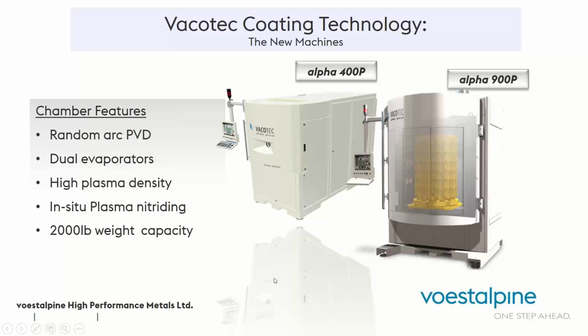It turns. One thing that you need to keep in mind in PVD technology, especially arc technology, is that it is a line of sight process. What does line of sight mean? What it sees, it can coat. So if it's hidden from the view of the plasma field, and the plasma field does travel in a straight line, it will not get coated properly. Yes, there is a little bit of wraparound, but it will not apply a significant amount of coating to actually protect the tool. This also applies to holes.